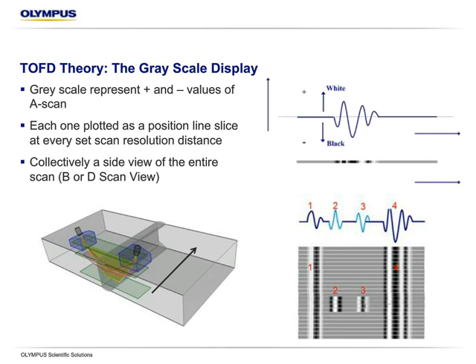So a little bit on the grayscale display. We start with an unrectified RF signal, and then we further manipulate the fact that we can see both a positive and negative component in order to set up very useful displays to be able to investigate large volumes at a rapid rate. If we scan something, we look at every signal, and based on our encoder or our data collection setup, we're basically going to take a strip line of data in black and white format for every millimeter or half millimeter, whatever we set, of movement down that weld.